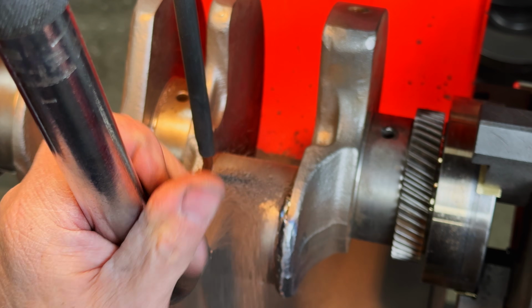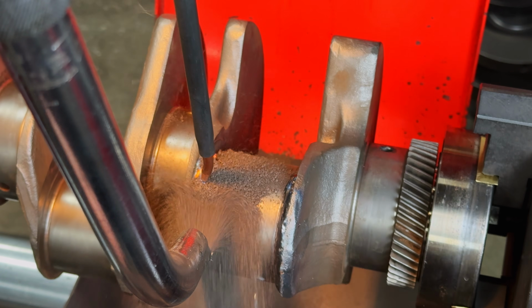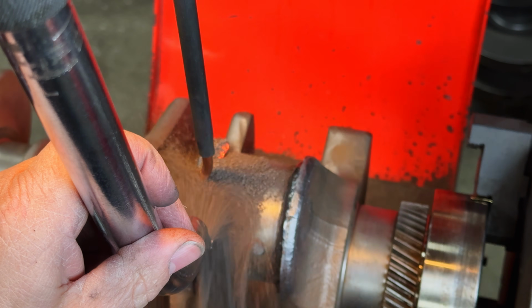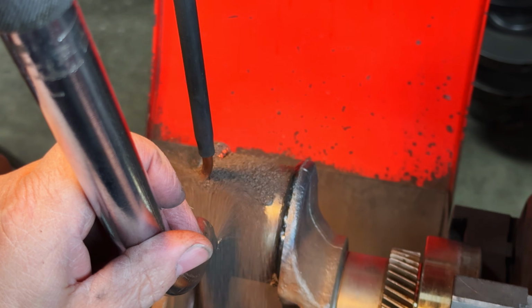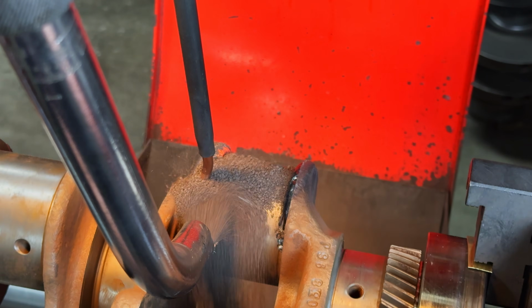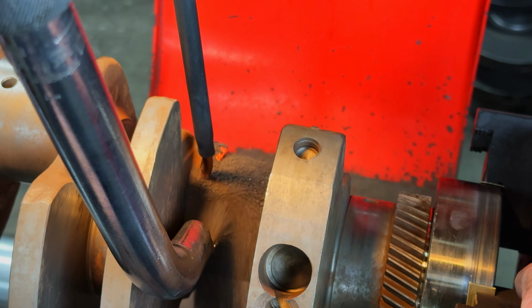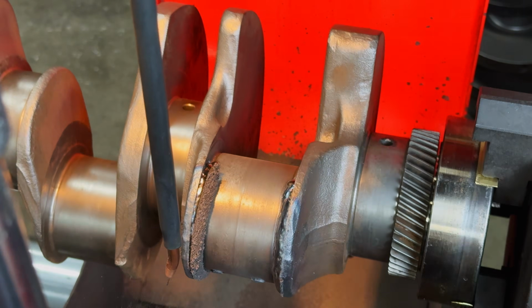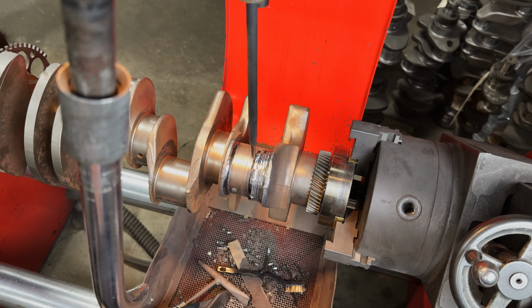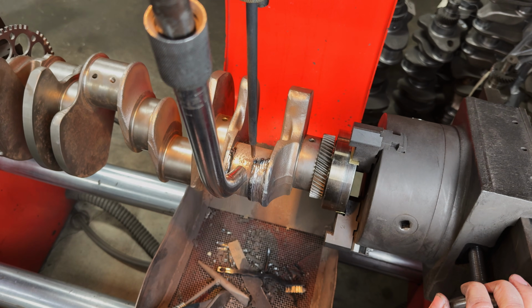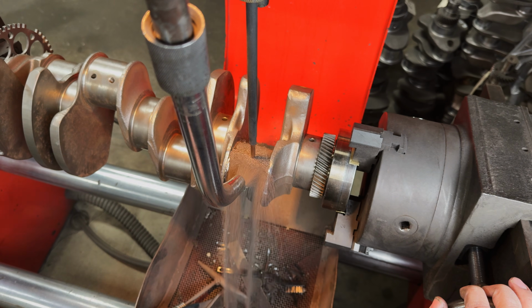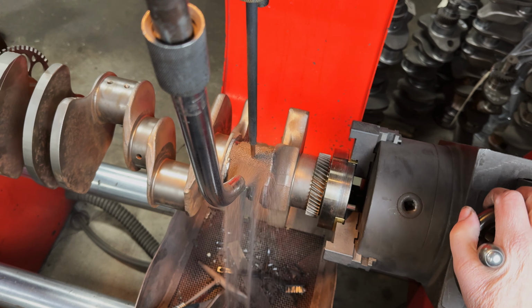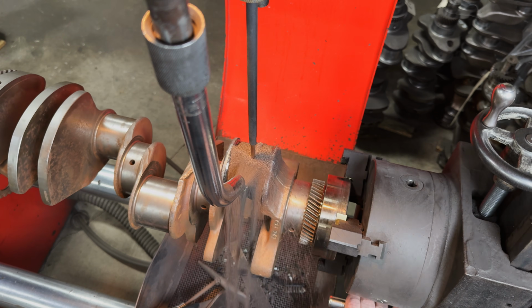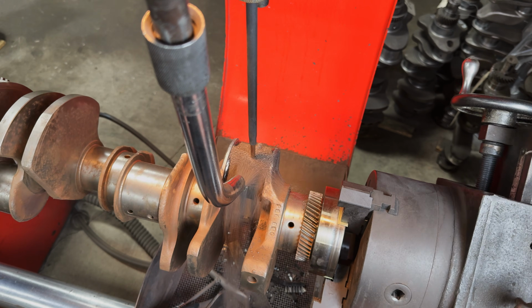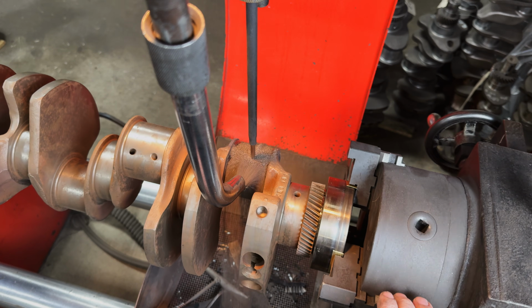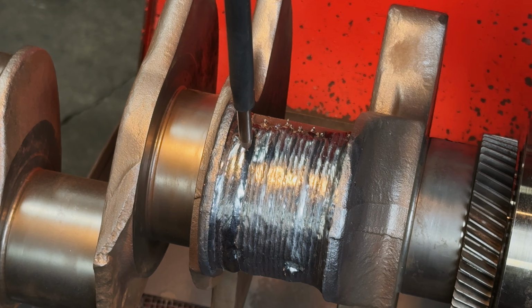The welder does have an automatic step-over feature, which moves the crank sideways, so each bead is laid next to the previous one. But since we're only welding one side of the rod journals, we have to manually jog it after each pass to place the weld exactly where it needs to be. There can't be any gaps between the welds. The first beads are laid along the edge of the journal to cover the radius. That area is critical. We want a tight bead right along that edge. From there, we continue laying bead after bead until the journal is fully covered. And then we will repeat the process for a second layer.